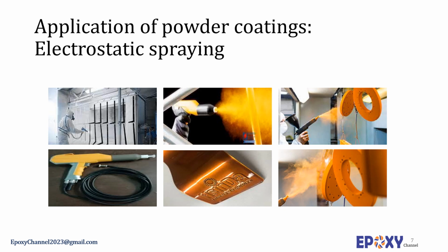In corona charging, ionization is employed to charge the powder particles, whereas in kinetic or tribocharging, the particles are charged by passing through tubes of special materials. The charged powder particles are deposited on the surface of the object with the aid of an electrical field. The filming is then finalized by stoving the object. Thicknesses in the range of 40 to 150 micrometers can be reached by electrostatic spraying powder coating.